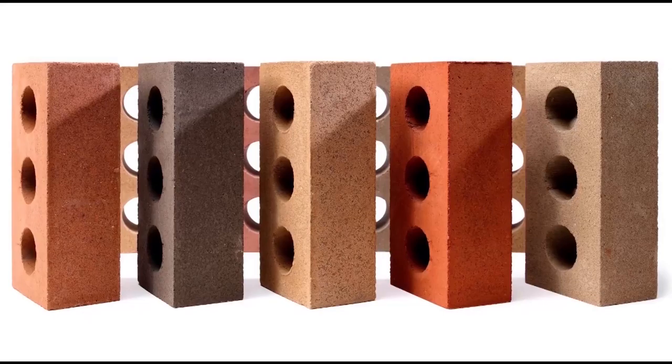Within face brick there are three different types. Face brick aesthetic is produced to be non-uniform in size, non-uniform in shape, non-uniform in colour — anything goes as long as it's rectangular in shape and has 17 MPa as a compressive strength. You get face brick standard, FBS — it's a brick that's got certain tolerance requirements that they have to meet, and there are no requirements on colour.